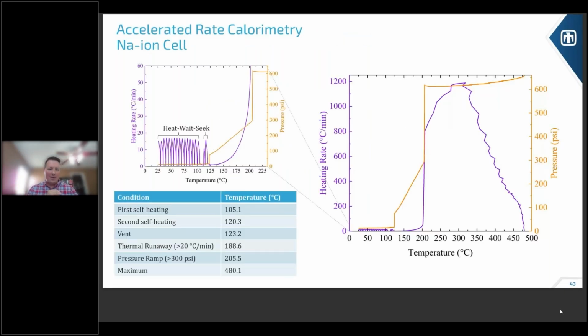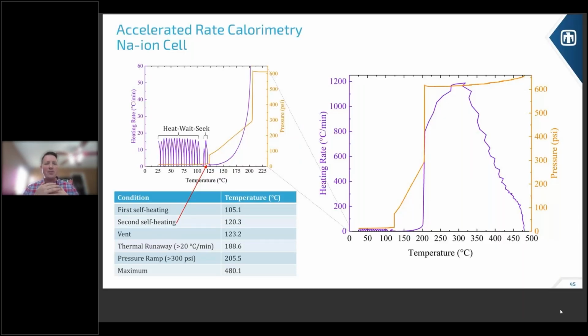Okay, so again, I put way too many slide transitions in this, so there's quite a few. I'll try to talk through this briefly. This is accelerated rate calorimetry. It utilizes what we call a heat-wait-seek mode. That heat-wait-seek mode just means that the ARC is looking for self-heating. It's all adiabatic. It pumps the heat up incrementally, and then it looks to see if there's a response from the cell. The cell is actually heating itself.